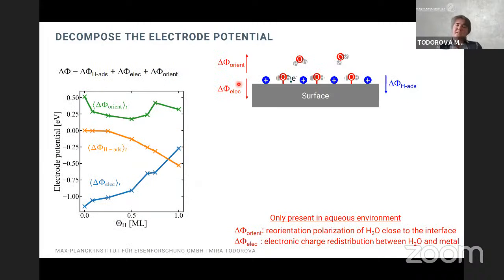When we look at the metal-water interface, however, there are two additional contributions which are attributed to the presence of the water. One of them is related to rearrangements in the electronic charge at the interface. So this would be, for example, the charge transfer of electrons from the specifically adsorbed water molecules, which were mentioned already in Jun Chen's talk, I guess it was yesterday, if I'm not mistaken, but also any kind of polarization effects. And there are effects that are related just to the reorientation of water molecules close to the interface.